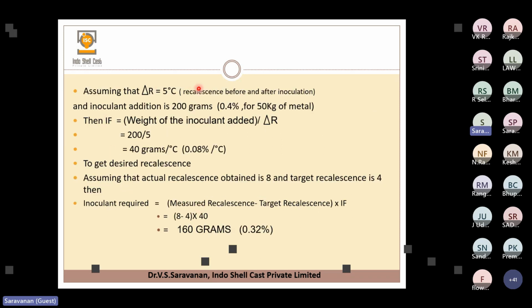For example, assuming that our recalescence before and after, that is the delta R, is 5 degrees, and the inoculant we have added is 200 grams, which is about 0.4 percent for a 50 kg ladle. Then the inoculation factor is 200 grams divided by this delta R. So that means 40 grams per degree C. To adjust per degree C of temperature, we need 40 grams of inoculant. That is about 0.08 percent per degree centigrade.